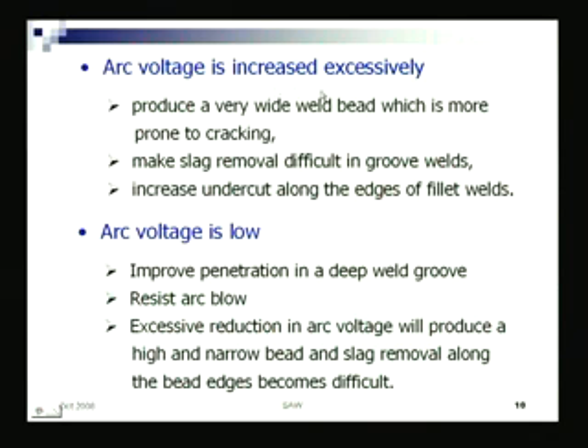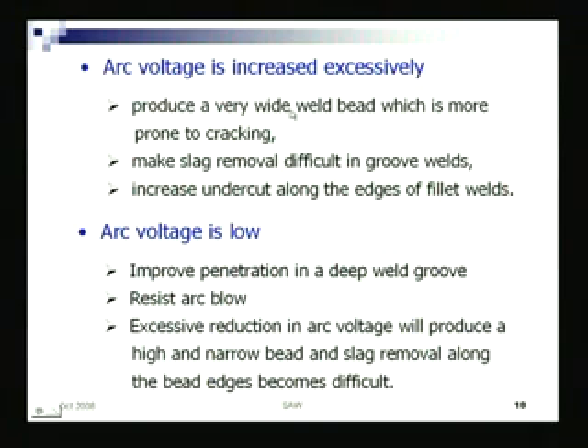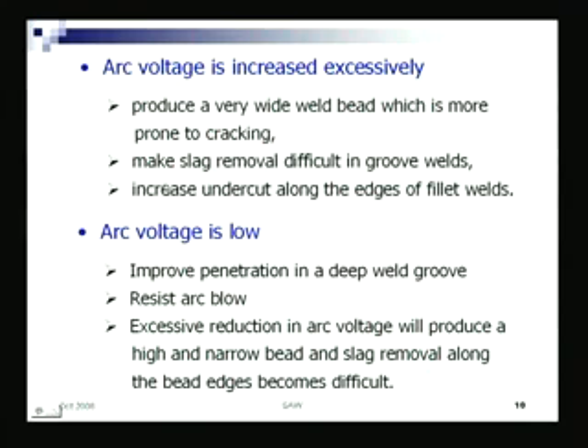If arc voltage is increased excessively, what does that mean? It means increasing the arc length, the distance between the electrode tip and the job is increasing. So what will happen? It will produce a very wide weld bead, and may make slag removal difficult in grooved welds - in a V-groove weld, the slag may remain sticking to that. It also increases undercut along the edges.